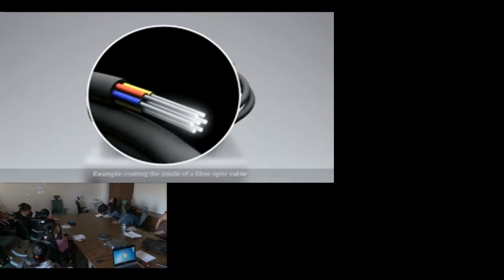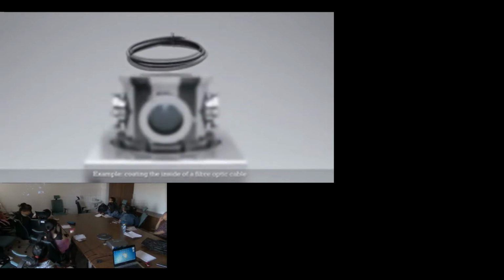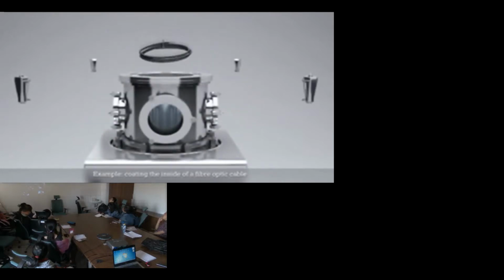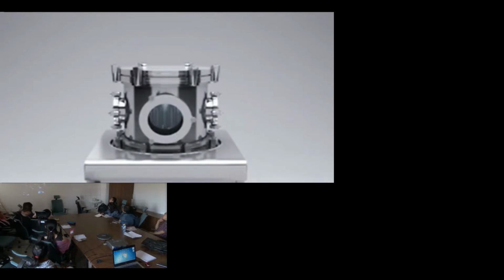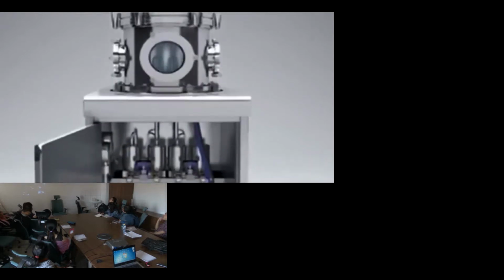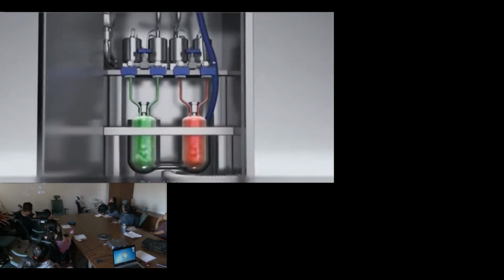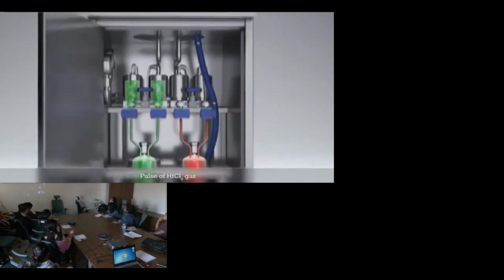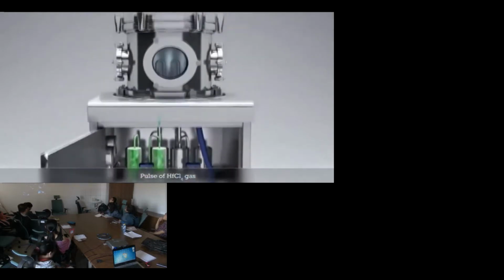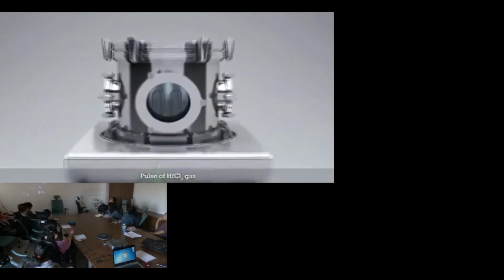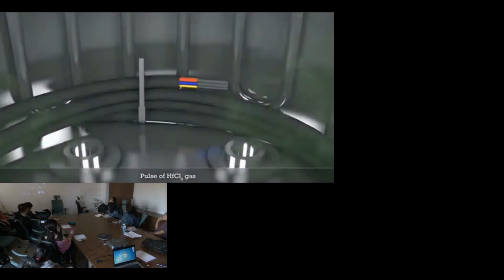So you put some sample inside. For example, here they put fiber optic cable. They put it inside the reactor, close it, pump it to achieve a vacuum. And here they have the precursors which are needed for this. So first they expose the sample to a pulse of hafnium chloride gas, and you will see what happens on the surface of this material you want to cover.